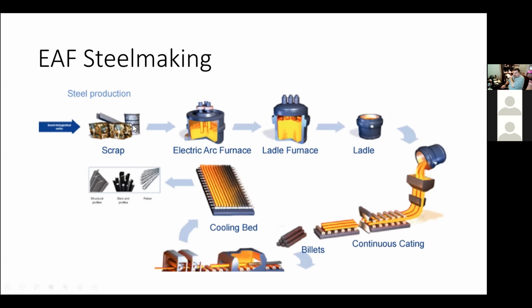So essentially here again, we've got our feed materials coming in. We charge them to an electric arc furnace. We melt them. We carry out some oxidation reactions to remove some of the impurities like silicon, some of the manganese, phosphorus. Then we move on to the ladle furnace, where we adjust the chemistry, we do alloying, we adjust the temperature, and we might remove some sulfur. And then that makes its way to the caster, where it's cast into semi-finished products.